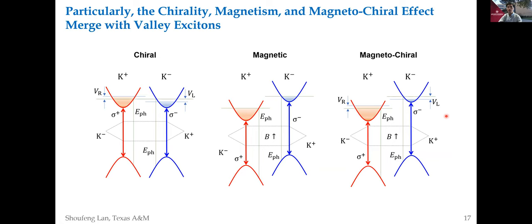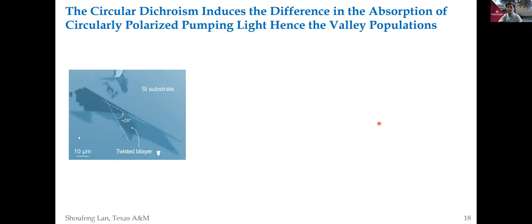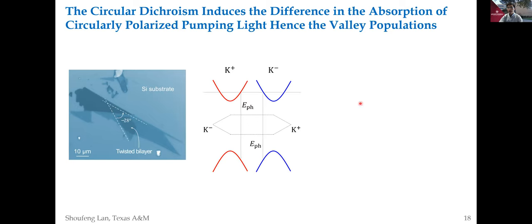First, let's study the chirality by placing the twisted WS2 layers on a silicon substrate, which is non-magnetic. In the WS2 layers, there are two valleys, K plus and K minus. When we shine a light with the photon energy of E_ph, the population of the two valleys will be different. The reason is that the twisting will induce a chirality, which has circular dichroism. So they will absorb different amounts of the LCP and RCP pumping light. Therefore, they will excite different numbers of excitons in the two valleys.